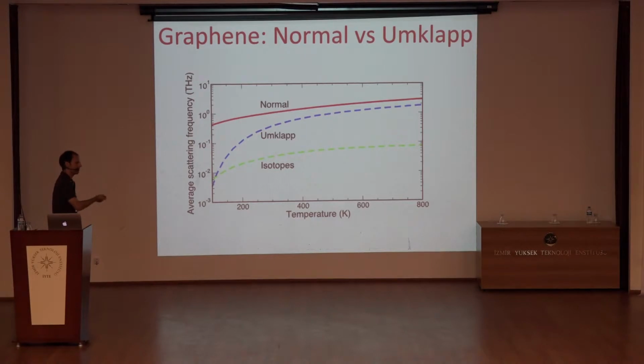So it's the most likely event you're going to see, not just at low temperature, where you expect some kind of Umklapp freezing so it's usual to see a lot of normal processes, but this behavior extends to room temperature and even above.